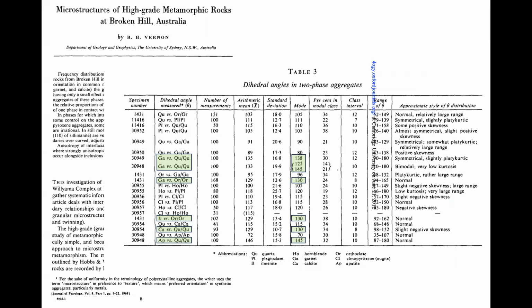So we've got the wrong way round. There are some anomalies. These 3 down here, the anomaly is actually very interesting, because these 3 here are mineral pairs where the structure and composition of the 2 minerals is completely different, like calcite and olivine, for example. You've got a carbonate and a silicate. Apatite and quartz, phosphate and silicate. Those are exceptions to the rule. And then garnet's doing something interesting here as well. This is something I want to chase up, because again, these anomalies are telling us something very, very interesting.